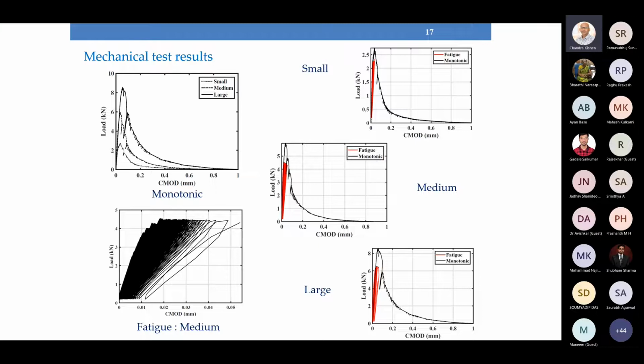We see the typical load CMOD response. Now the test was performed under CMOD control, and these are the load CMOD plots for small, medium and large size beams. What we see is an initial linear response, and then just before the peak load, a non-linear region deviating from linearity, and then it reaches the peak load. After the peak, we see the typical softening response for all the beams. This is for the monotonic load.